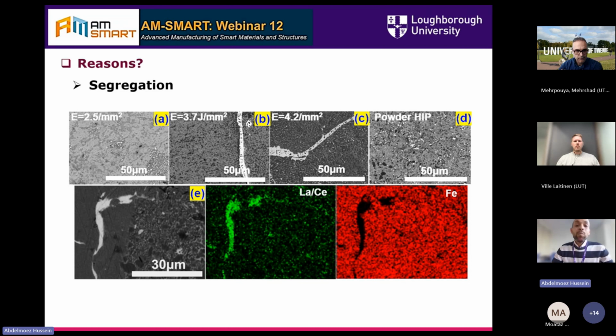So the reasons why we lost the first order, sorry. This is because there is a segregation happening from the material. So this segregation affects the chemical composition of the material. So the starting nominal compositions that we started with has been lost in segregation, secondary phases, probably oxides, probably iron, probably lanthanum. So secondary phases are affecting the phase transition itself.